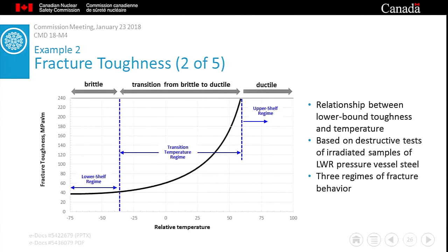However, when spring temperatures arrive, a sudden pressure increase might make the hose leak a little bit, but it would not rupture. Returning to the example of reactor pressure vessel steels, once the material reaches upper shelf temperatures, it exhibits purely ductile behavior. The fracture toughness is quite high, so even if a crack existed, the tube would resist its growth. Under these conditions, the crack will not grow unless the load is increased.